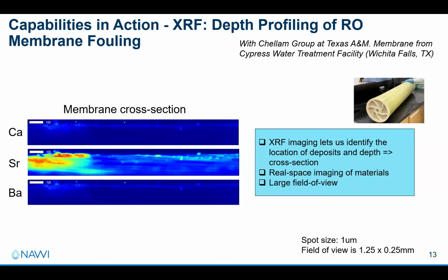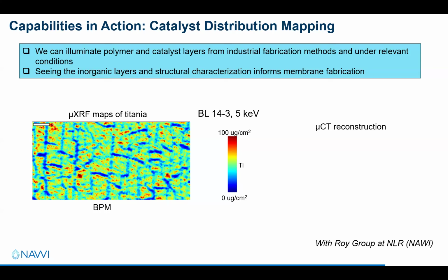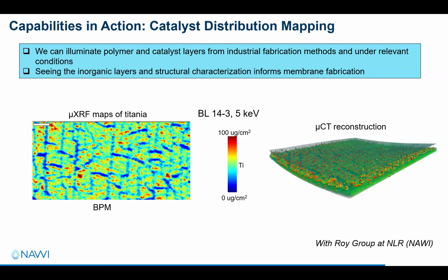There's also XRF. So what you see here is a membrane cross section. So it's 1.25 millimeters across and then 0.25 millimeters down. And we looked at calcium, strontium, and barium and saw that they have different depth penetration throughout the membrane. You can also look at the top surfaces of these materials and just look at the distribution of your species on top of these membranes. And let's see. Oh, I don't know why it's not showing up. Okay, well, then there's also micro XRF. You can basically map the top surface and get information about the distribution of your catalyst, so in this case titania, over the top surface, and can thereby get information about how well your processing is working.